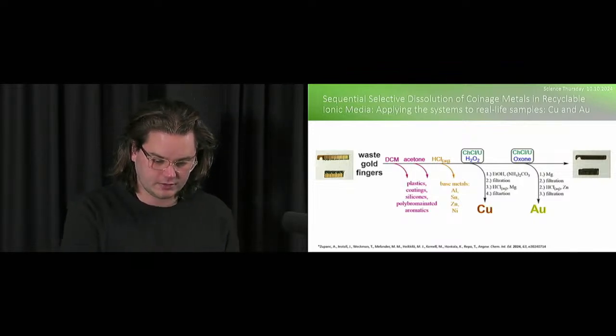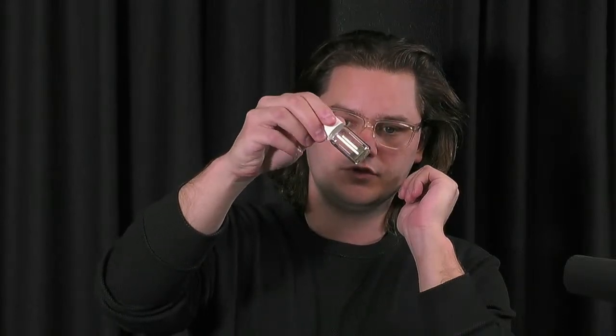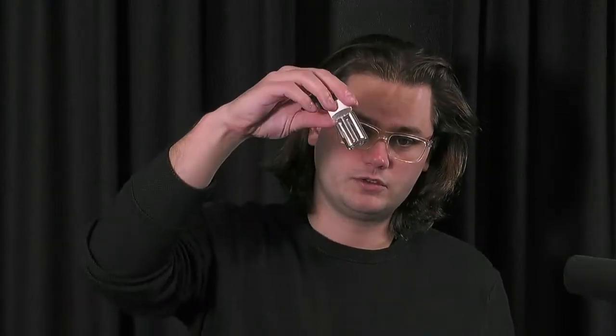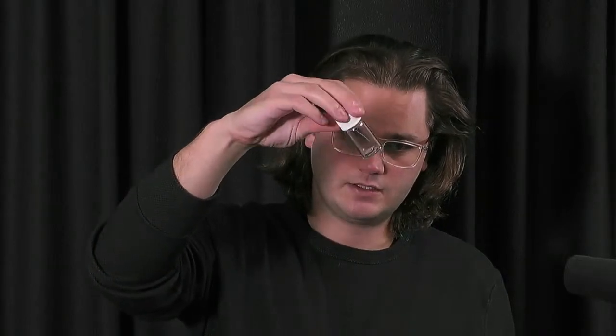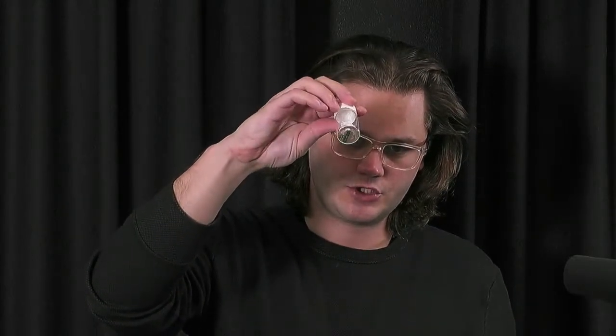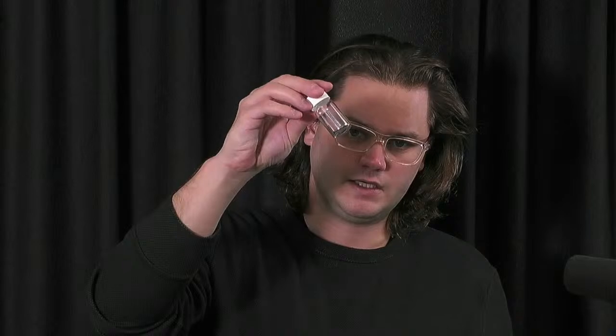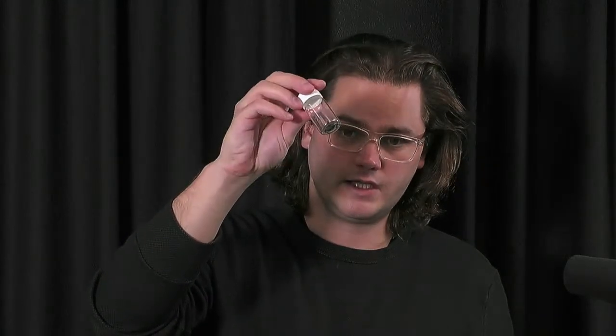So how these materials look before and after, you can see these are some parts of the computer motherboard. You can see a very shiny layer of copper, and after the dissolution there is no more copper left. There is only this plastic composite there. And for the gold fingers, you can see very nice shiny gold fingers before the dissolution, shining of real elemental gold, and after the dissolution all the metals disappear. There might be a little bit of nickel left, which was a very beneficial thing for us.